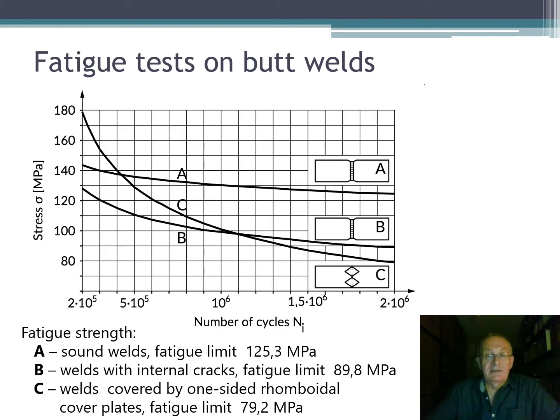Fatigue test result on butt welds. Three types of samples were used in the test. Sample mark A means sound welds of good quality. Fatigue limit was estimated at 125 megapascal.